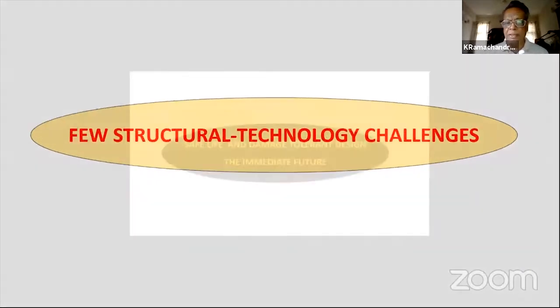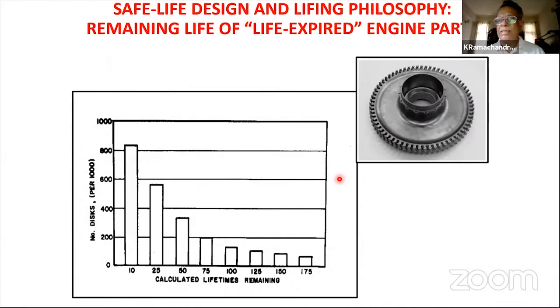We look at a few structural technology challenges, and we are designing the engine today on what is called a safe life philosophy. We test the parts, we test the material, and we know what is the safest temperature, safest stress, and stress excursions that will result in damage to the component. And we know that number. And beyond that number, all the parts, which are very expensive, manufactured from the same batch, shall have to be removed and inspected. And if even one of them has failed, a 0.8 mm crack has developed in any location in the part, the whole batch, say for example, you have manufactured 200 discs in the same batch, all the 200 components have to be thrown out, which is simply a stupid thing to do. It's not very cost effective. Each one of them may be a couple of crores, depending on the complexity.